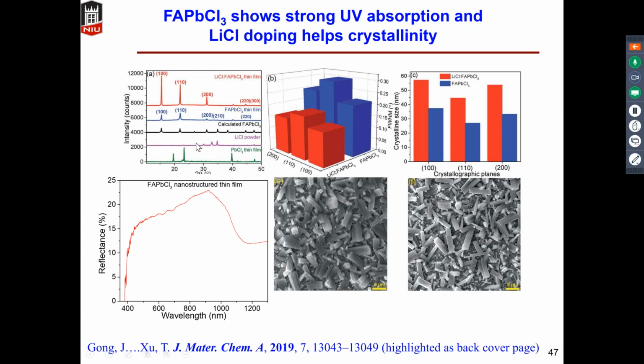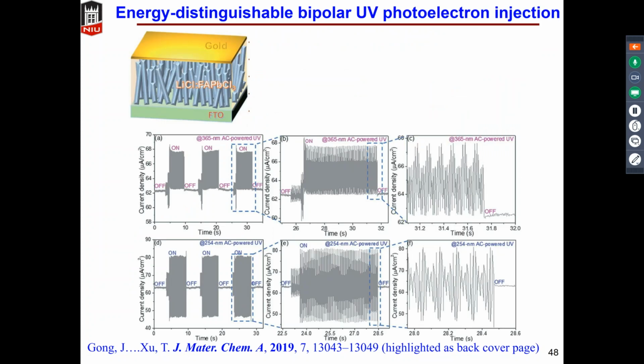So here are the X-ray diffraction spectra of lead chloride, lithium chloride, the FAPbCl3 thin film, and the lithium chloride doped FAPbCl3 thin films. This all indicates that we get much better crystallinity with the lithium chloride doped formamidinium lead trichloride. So we made this thin film into this optoelectronic structure, and we measured their response to different UV wavelengths. For 365 nanometer UV, it was powered by AC voltage, and we found that the photoelectric signal is also oscillating at the same frequency as the AC power.